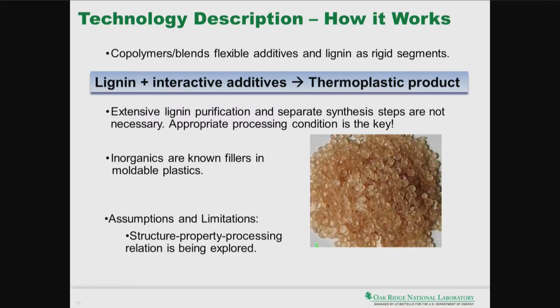Now, in this particular technology, we don't need extensive lignin purification. The reason for that is we are not preparing a carbon precursor or some other specialty or fiber-forming material at this stage. So inorganics that are present in lignin can stay there as they are, as long as they are not very high in volume percentage. So as-received lignin from industries that is commercially available can be used to make this kind of product. And in fact, in some thermoplastic materials, for example, polypropylene, people use some inorganic chemicals, for example, calcium carbonate, for controlling the crystallization kinetics. So these lignins can be used with additives to make thermoplastic product by appropriate processing conditions.